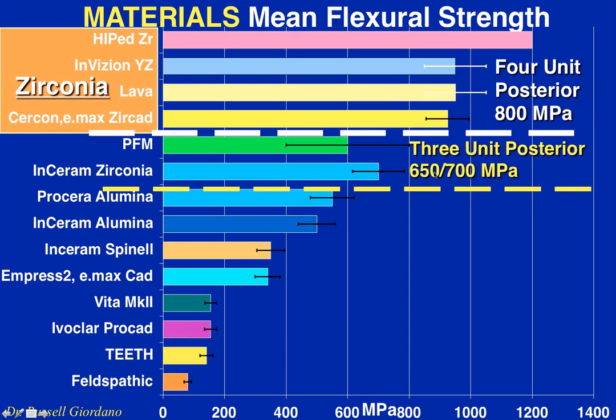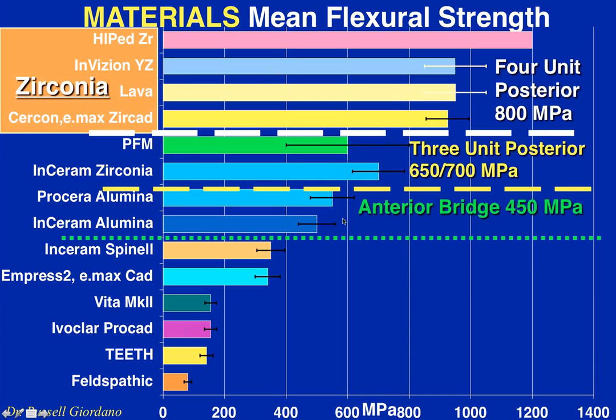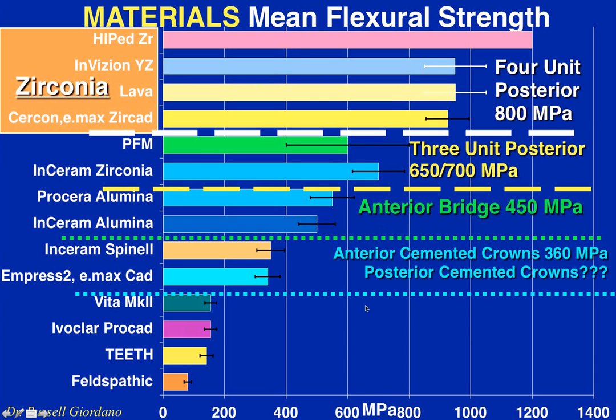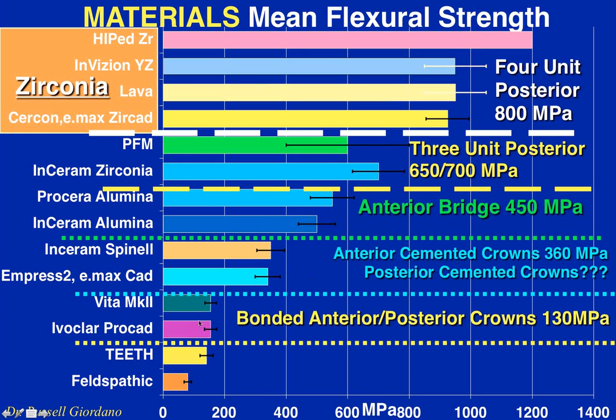As we go down, we get different application areas for these materials. We have in-ceram materials, we have alumina, Emax materials as far as cementing. Now we go down here, our original monolithic block, our VITA Mark II, even though the strength value is very low compared to a BruxZir zirconia, let's say, when we bond these restorations into place, and if they have adequate thickness, then the load-bearing capacity is sufficient to work just as well in many cases as a zirconia material.